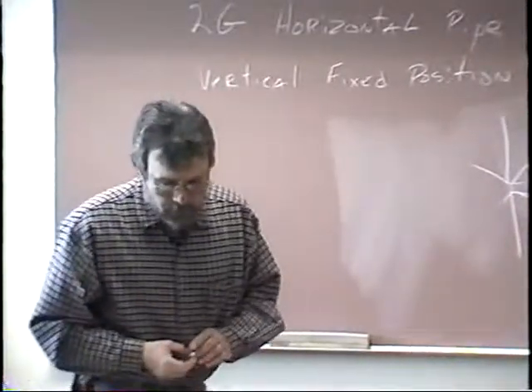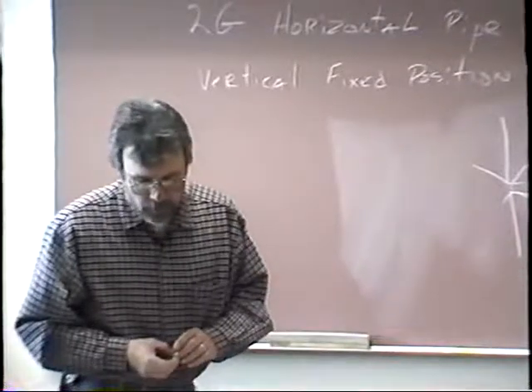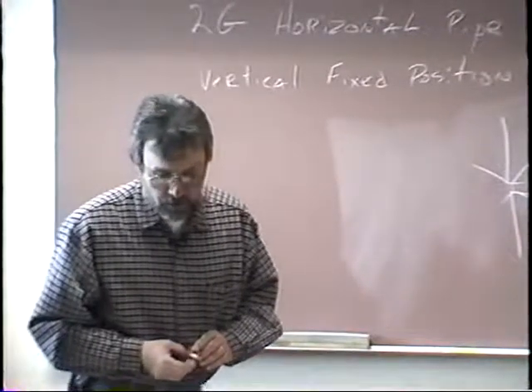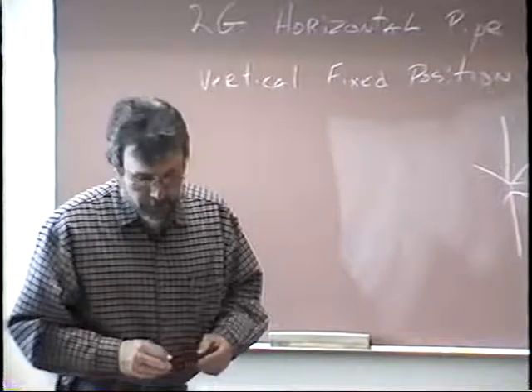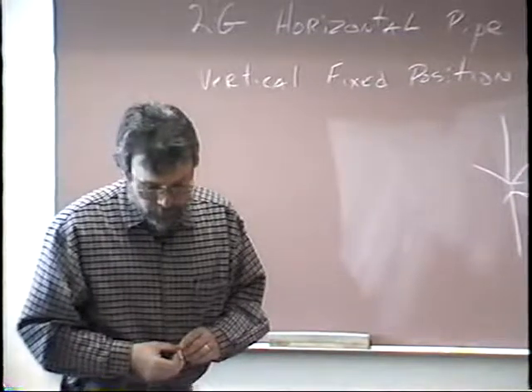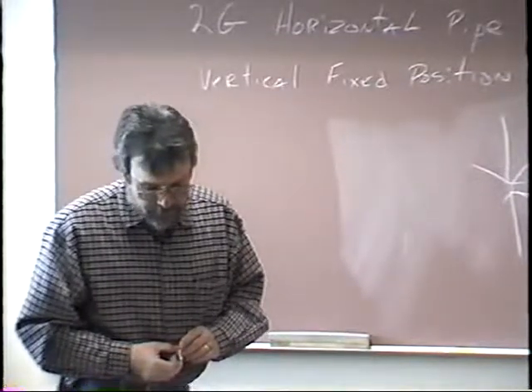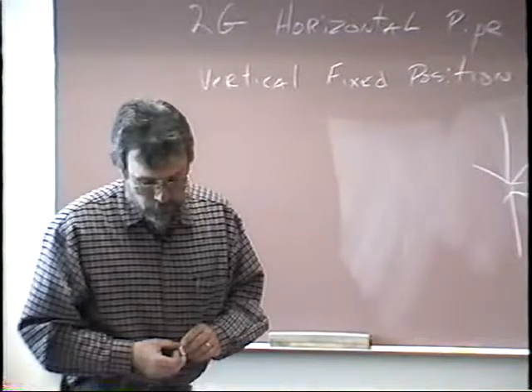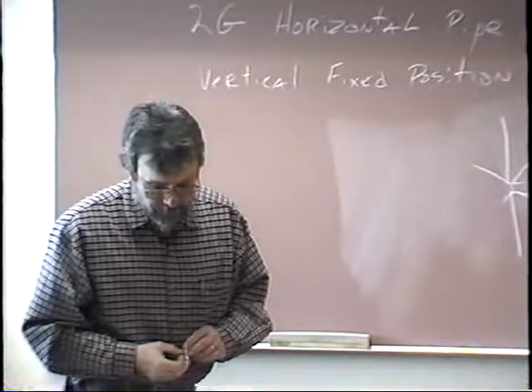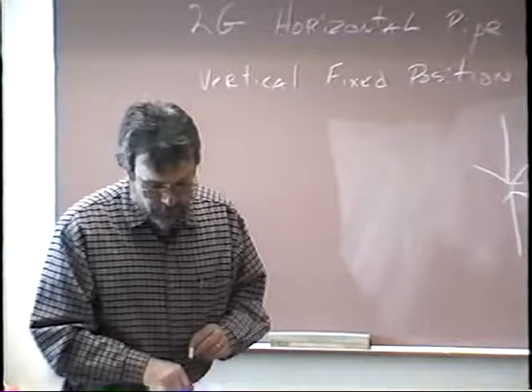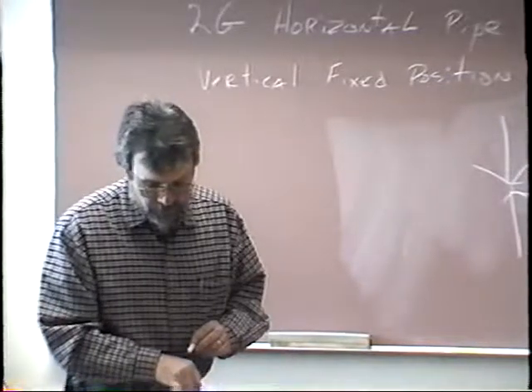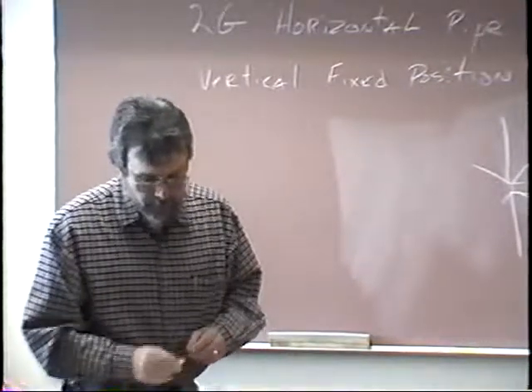The electrode angle for welding the root bead in the horizontal 2G position is shown in figure 9.3. This angle should be maintained when welding around the entire pipe. The side angle of the electrode should not deviate more than 5 degrees from the horizontal plane. Any further deviation can result in undercutting, which in turn can cause cracking, especially in heavy wall pipe.